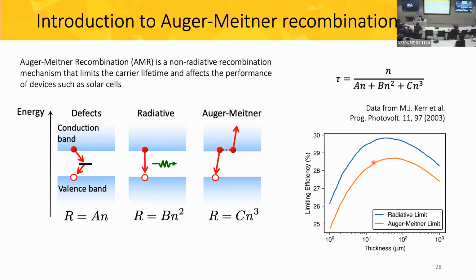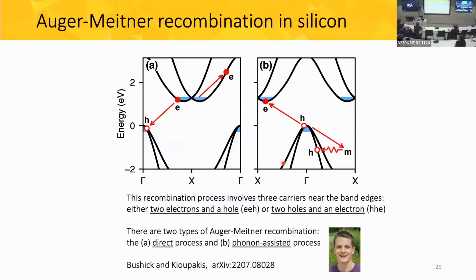The reason it's important for silicon is because the band gap is indirect, so you don't have a radiative rate, and you don't have many defects because silicon is a very pure material. So the dominant process in solar cells today is actually the Auger-Meitner process. And so our goal is to understand how the Auger-Meitner process occurs in silicon. Now, let me show it to you in energy-momentum space, because there are many ways it can happen.